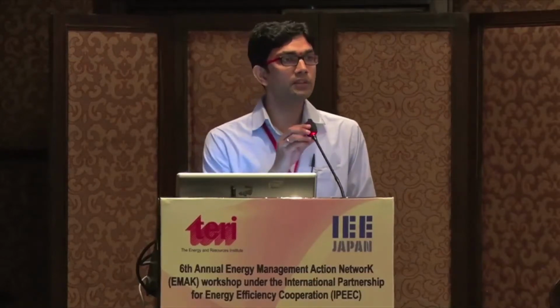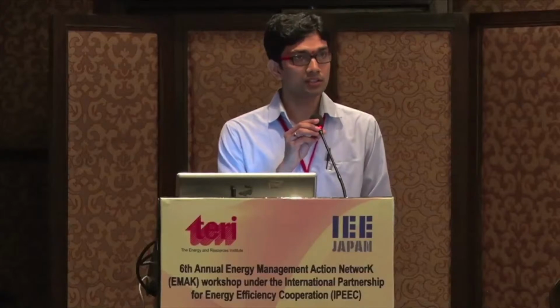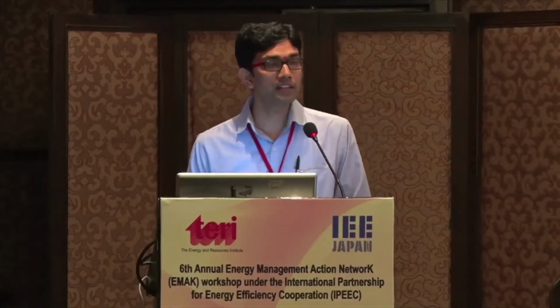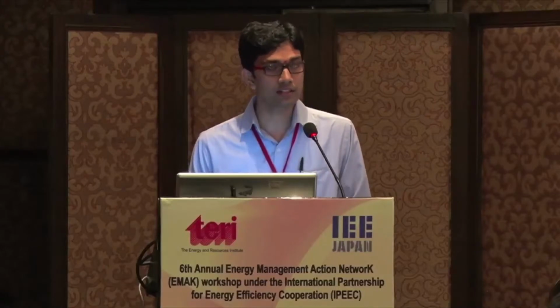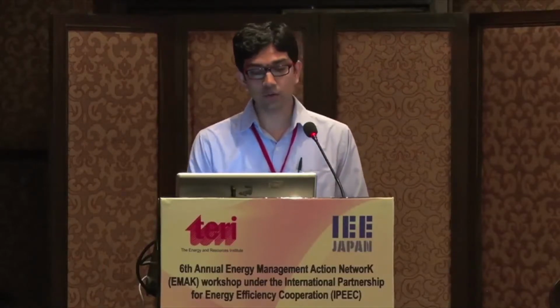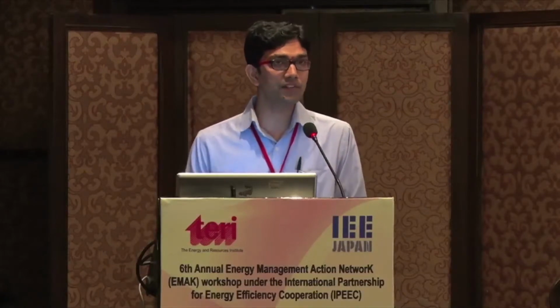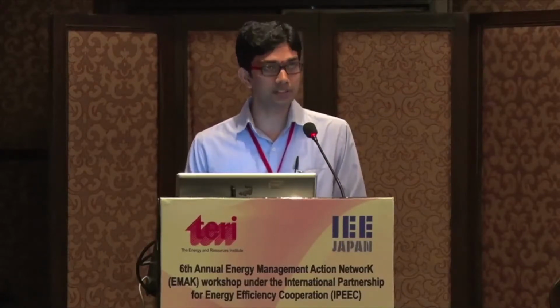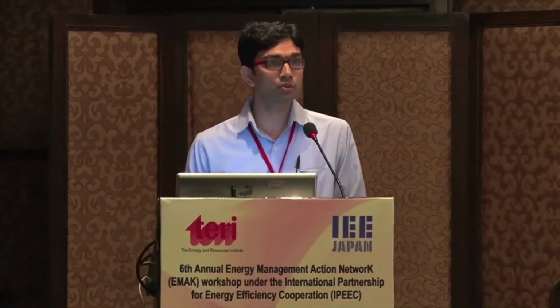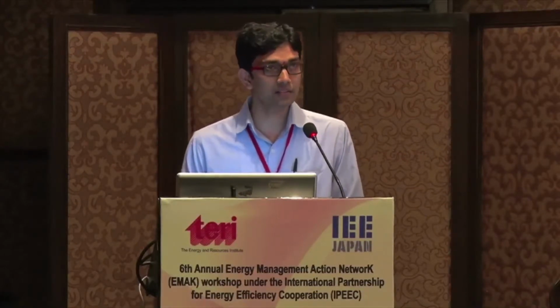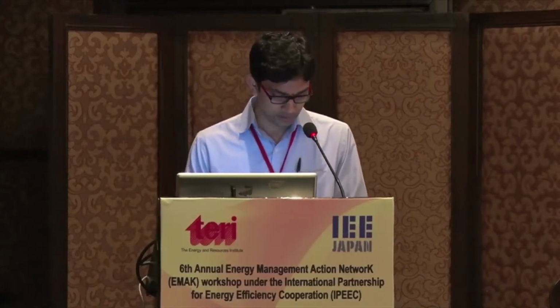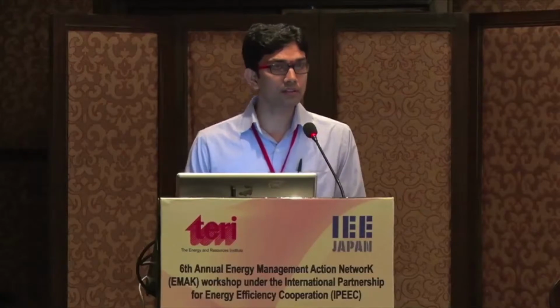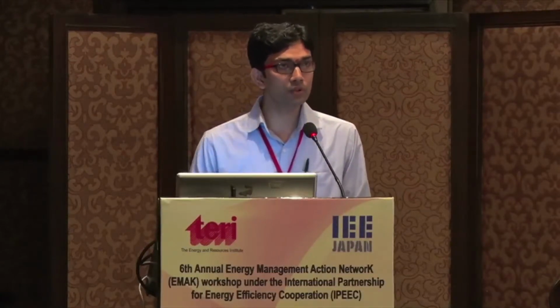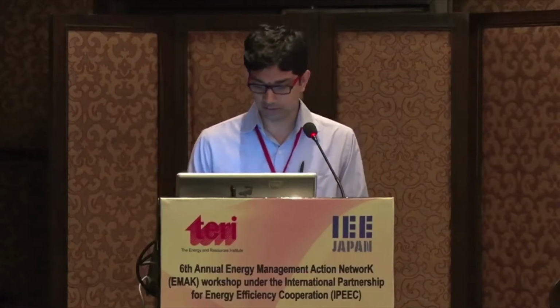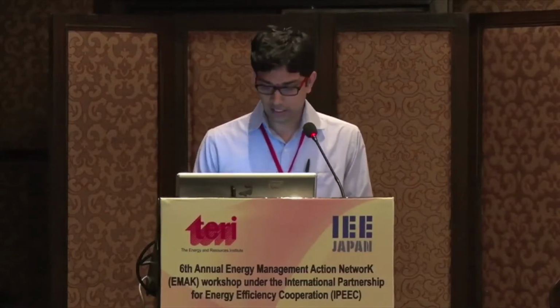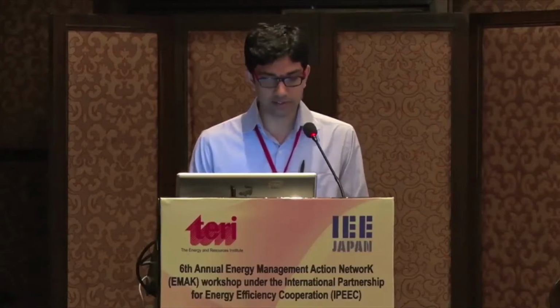If we consider 20% of this dry flue gas loss to be recovered with the help of installing a waste heat recovery system or a recuperator, we are talking of increasing the efficiency of the PNG-fired furnace to as high as 53%. This is comparable to the efficiencies of induction billet heaters or induction furnaces, and therefore it is very opportune for forging units to go for waste heat recovery. However, I'll talk about the barriers and the technology-related issues later in the presentation.